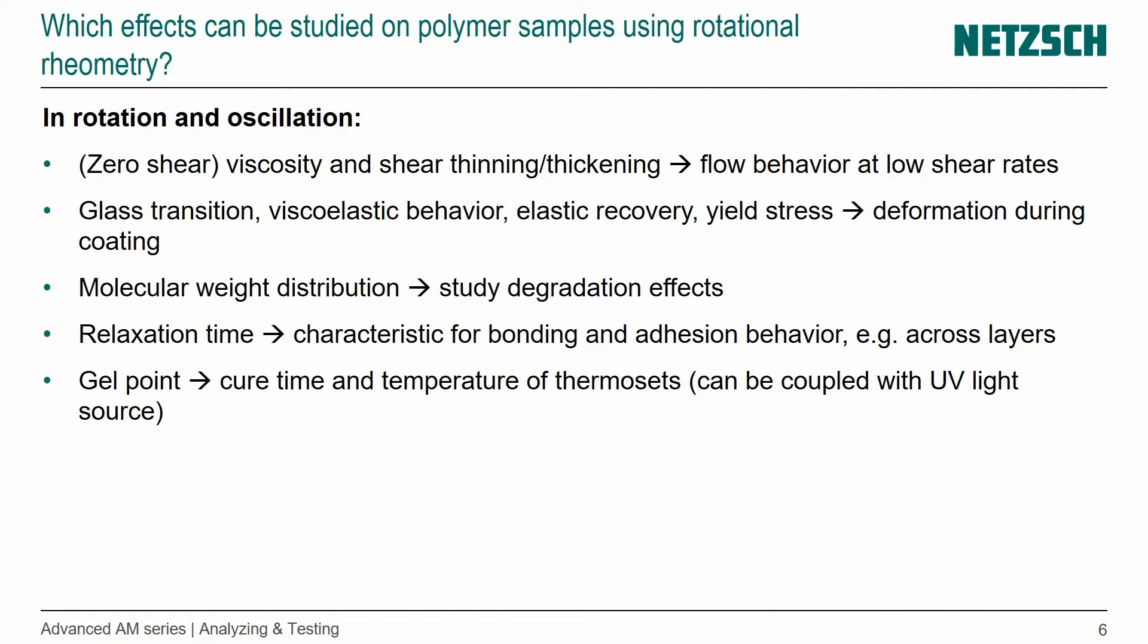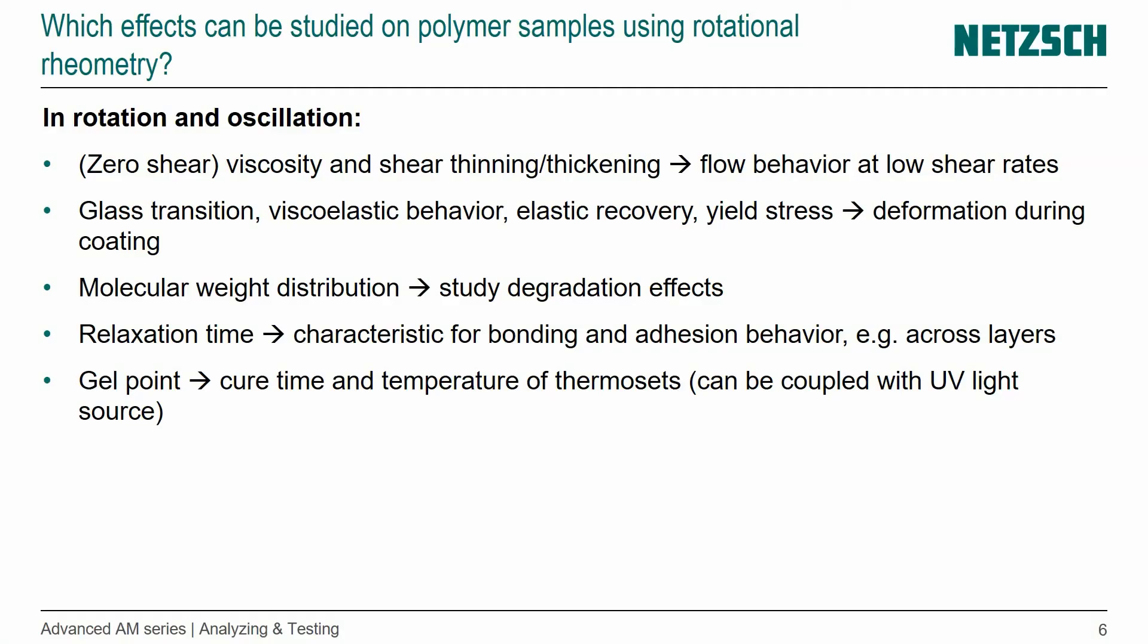Which effects can we study with that on a polymer sample? We can get the viscosity, the shear viscosity where we don't have an effect of shear rate. We also get the shear thinning and thickening. That is something for material extrusion, for example. We also get the glass transition, viscoelastic behavior, elastic recovery, yield stress.